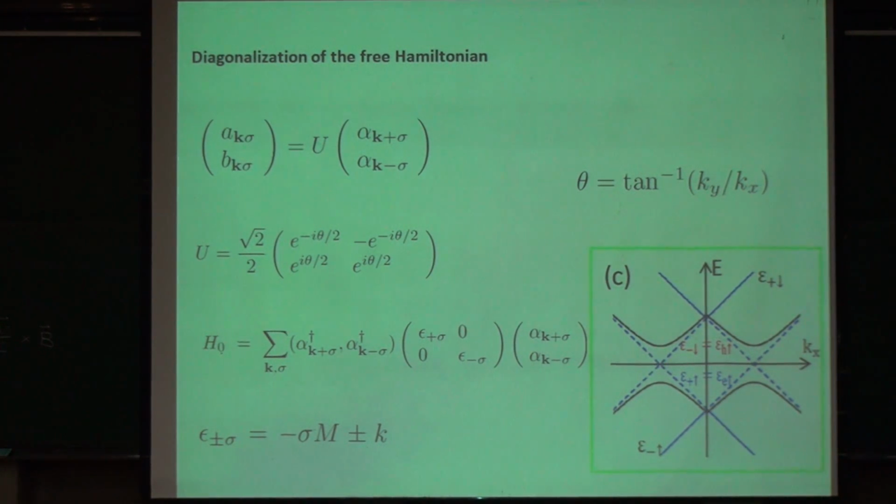Then the Coulomb interaction will play an important role, because once you have degeneracy, the other part of the Hamiltonian becomes important. And the Coulomb interaction, the attractive interaction between particle and hole, will create an energy gap around these crossing points. That gives you this black curve. Due to this energy gap, this is the gap for the spin superconductor, just like the energy gap for a charge superconductor at the Fermi surface. There's an energy gap. Here you also have an energy gap.